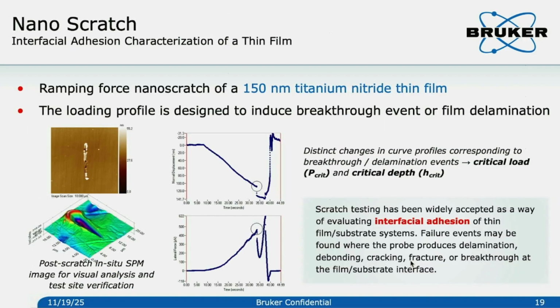Okay, so this is another example for a 150 nanometer thick titanium nitride film. You can see there is the big jump. This is what we call the critical load. This is about interfacial adhesion measurement.